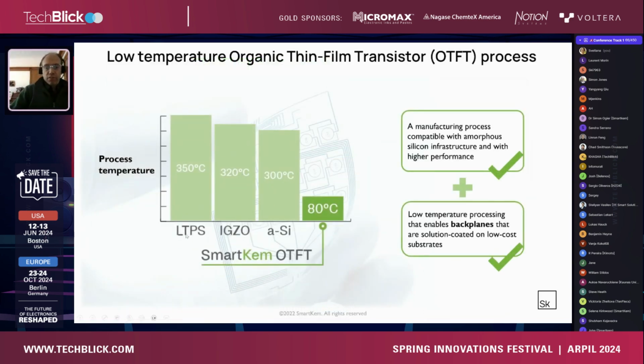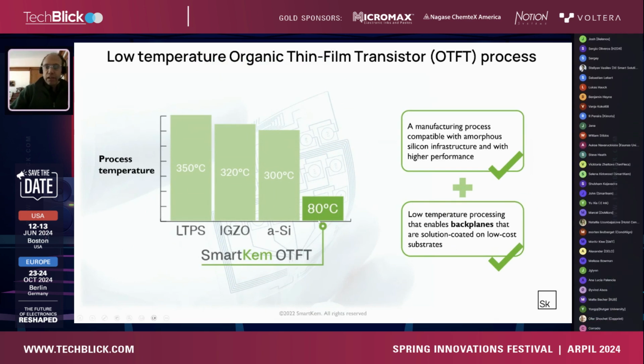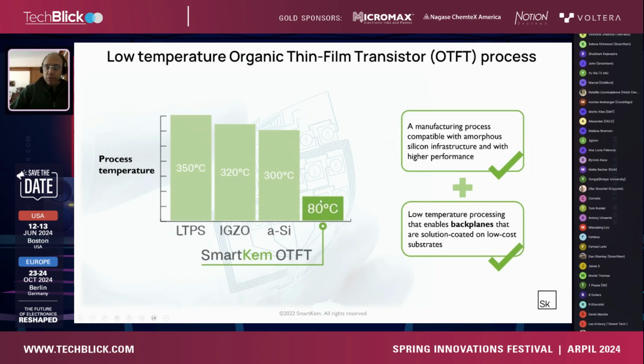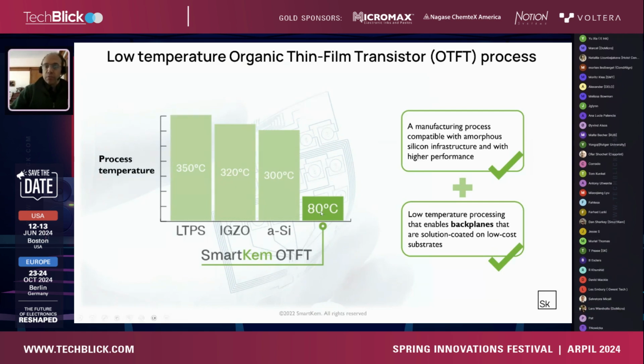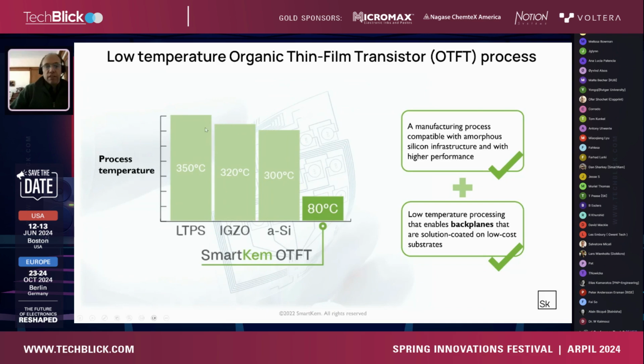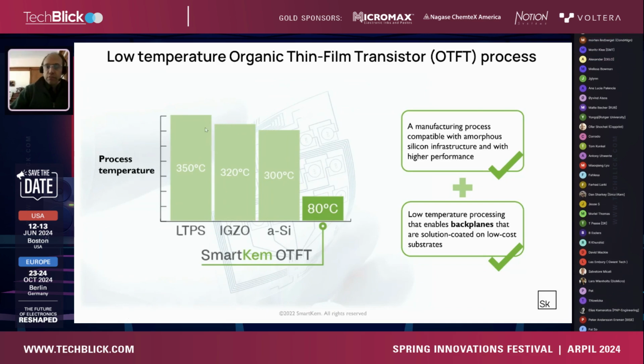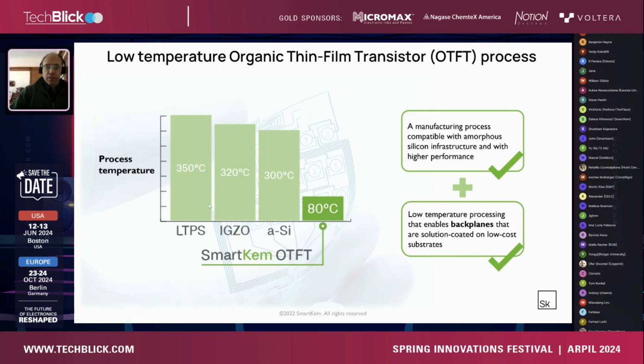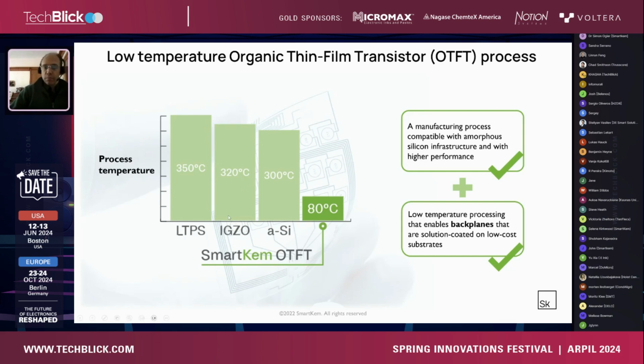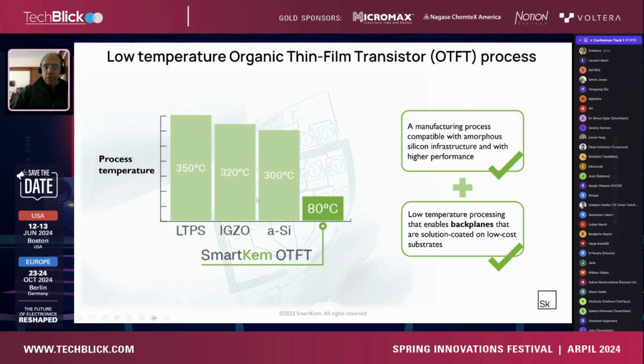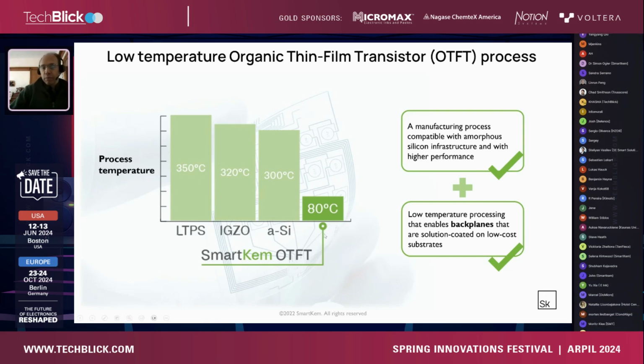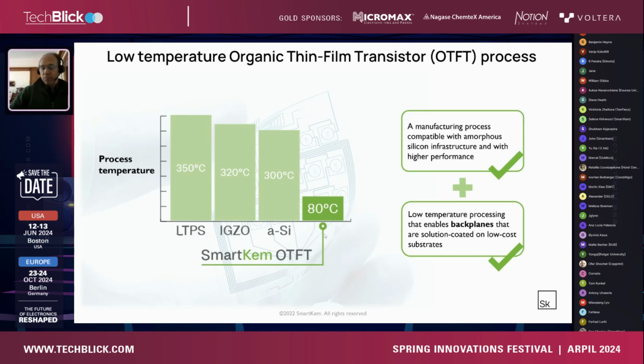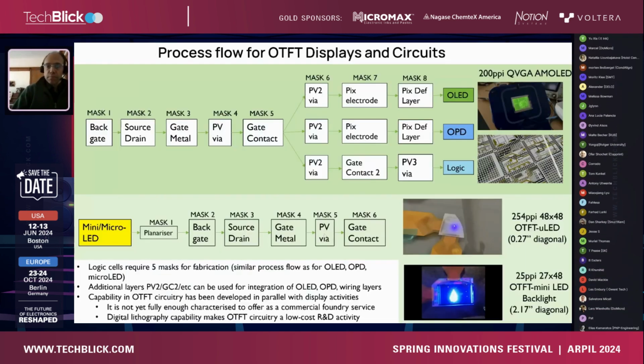So compared to other thin film transistor technologies, our temperature of processing can be as low as 80 degrees C, typically below 150 degrees C, but we've demonstrated down to 80 degrees C as a proof of concept. Most other TFT technologies require processing in excess of 300 degrees, even towards 400 degrees. And that is mainly for the PECVD process for putting down the silicon nitride dielectrics, which tend to become worse if you lower the temperature. So hence they're not very plastic compatible, and you have to process the backplane before you're doing the rest of the device. So this is the main differentiator in that we can use this to our advantage, and people can use it for making devices on novel types of plastic substrates or making devices in novel ways.